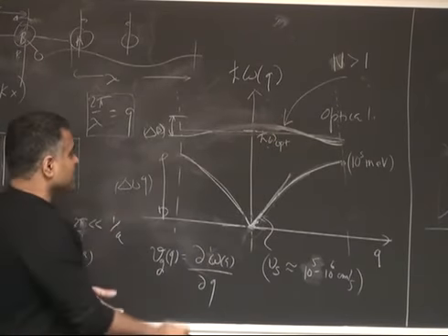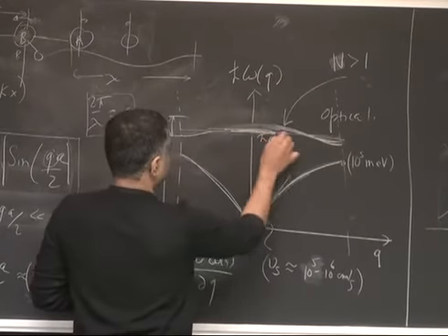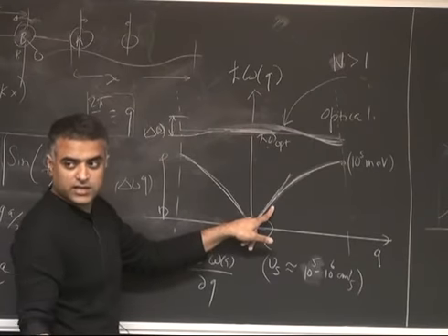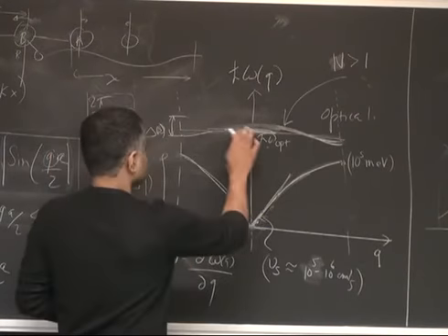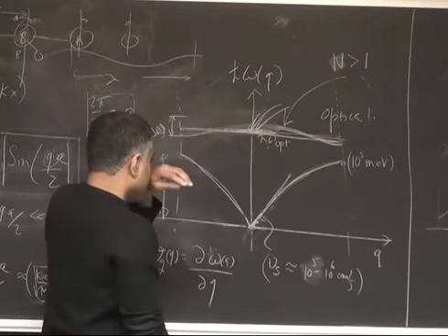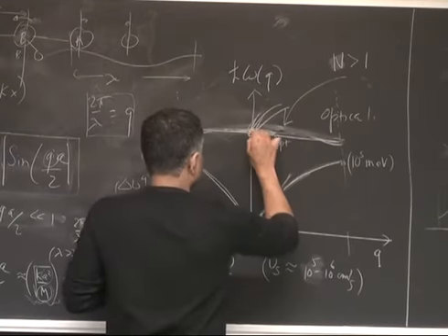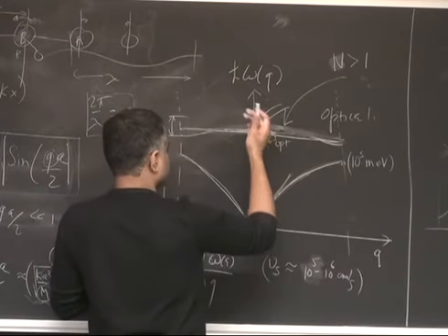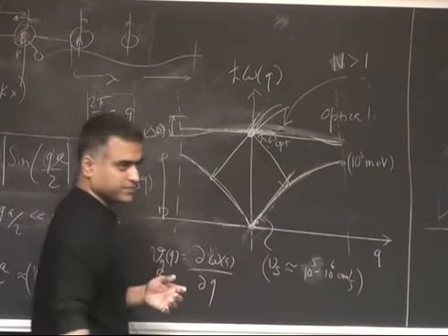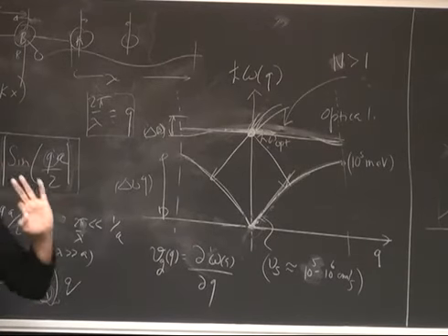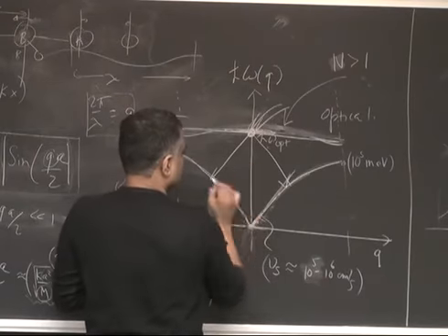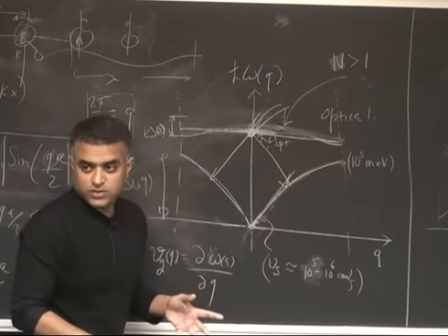So clearly, what one needs then is for the optical modes to go into the acoustic modes, because the acoustic modes move with the speed of sound, and they can carry the heat out. So what happens is you dump your energy into these optical modes first. The electrons dump their energy there, and then there is a time scale in which, for example, this optical mode has to decay into 2 acoustic modes. One phonon mode has to decay into multiple acoustic modes such that energy is conserved and momentum is conserved, because they're always conserved.